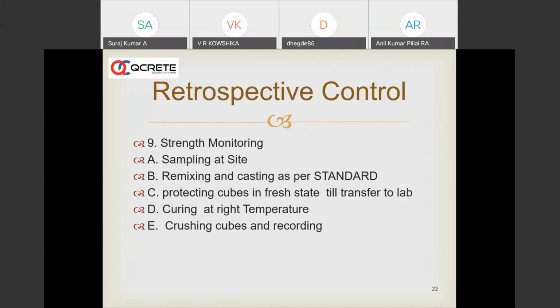During the fresh state, we also check yield, which is in other words checking the plastic density of concrete, and this plastic density is compared with the theoretical density. Also, for trucks, we take the initial truck weight and then the final truck weight, with and without concrete, and compare the concrete weight with the theoretical density, just to check whether the plastic density and yield that we are getting is right. So these are part of the immediate control.